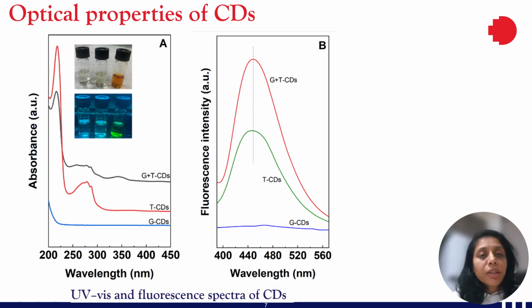The optical properties of these carbon dots were studied using UV visible and fluorescent spectroscopy. An absorbance peak at 275 nanometer of tryptophan carbon dots and glutamic acid and tryptophan carbon dots is due to the n-pi star transition that contributes to the photoluminescent signals. However, the n-pi star transition in glutamic acid and tryptophan carbon dots is much broader compared to tryptophan carbon dots and may be due to the formation of numerous surface defect sites. It also displayed an additional absorption band centered at around 350 nanometer, which is probably due to the formation of new electronic states.